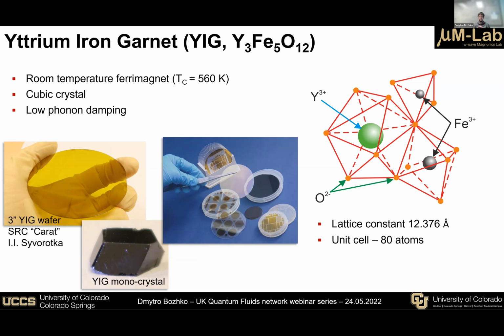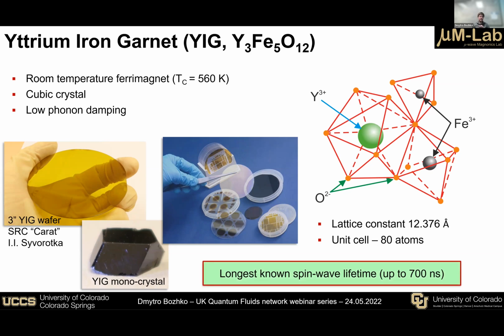It has up to about 700 nanoseconds lifetime at room temperature, and at low temperatures it could even go beyond 1 microsecond. So this is already phenomenal. There were no other materials with such damping discovered so far. That's why we stick to this material.